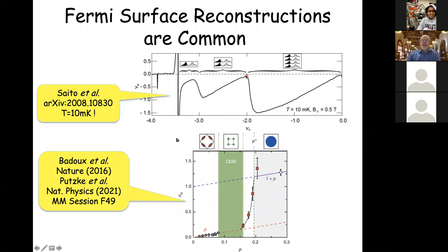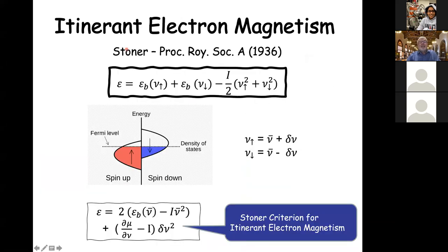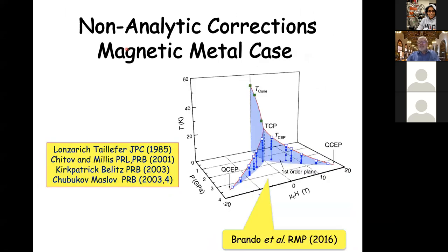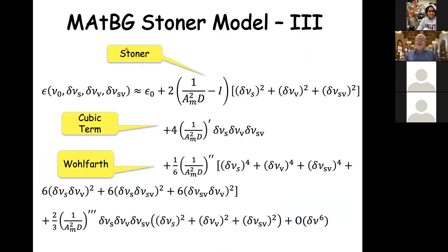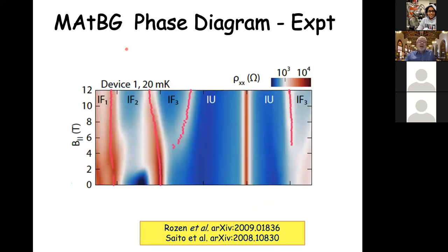The Hall effect, of course, measures the carrier density in the partially filled band and tells whether the Fermi surface is hole-like or electron-like. And so this picture of this region of filling factor between -2 and -3, where the strongest superconductivity occurs, is pretty well established. And it seems like superconductivity occurs in a flavor polarized state, most likely a spin polarized state. And I'm going to skip this. There are interesting analogies between magnetism and generalized magnetism associated with spin and valley as generalized spin indices in this system that are echoes of what happens in metallic magnets.